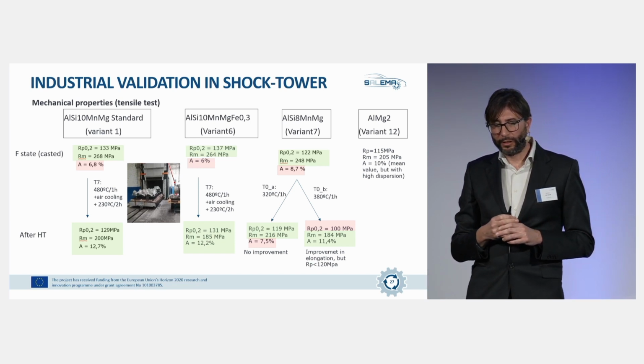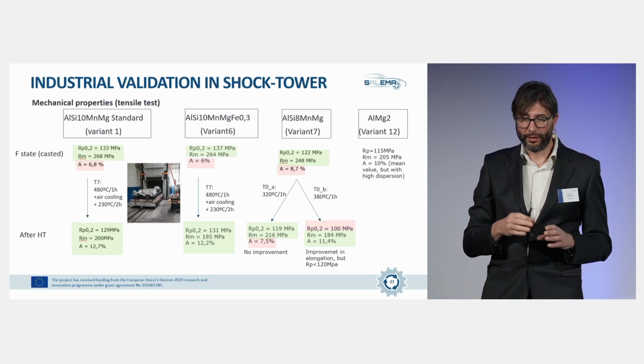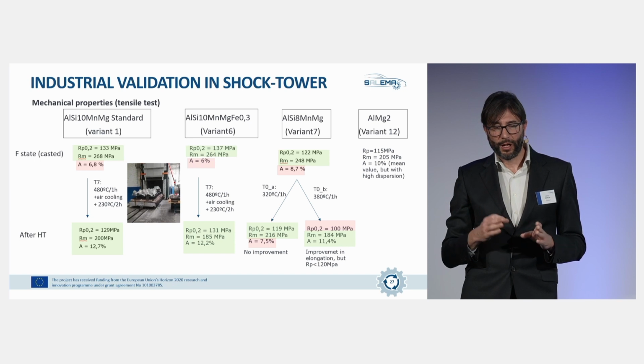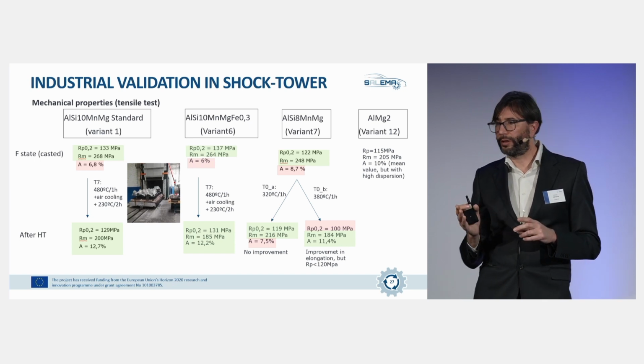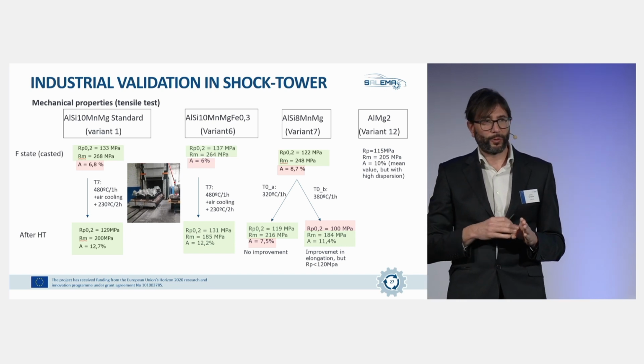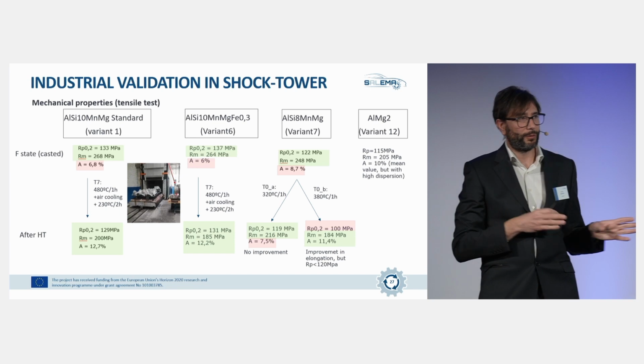Then for variant 7, instead of a T7 heat treatment, an annealing treatment was tested, and with that, 2 different temperatures were tested at Fagor, 320 and 380. With the 320, 1 hour, we observed that mechanical properties remain almost unaffected. So actually, we are losing ductility and a little bit of yield strength. And with the 380, we reach the minimum required elongation. So we were successful in getting more ductility, but unfortunately, at the cost of losing some hardness, some yield strength that went below the minimum requirement.